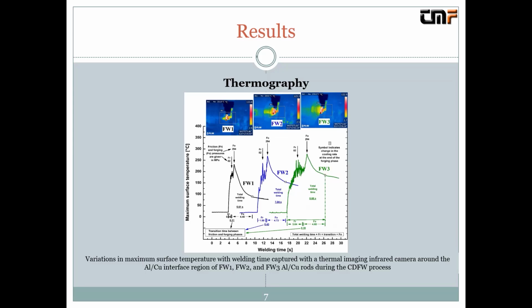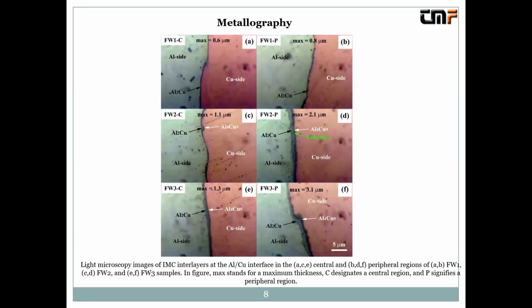And what's the importance of measuring those temperatures? It's to try to combine that information and to explain the kinetics of formation of intermetallic compounds. So in that manner, we have the higher temperatures for the third sample, and as you can see, all these changes which we followed were divided into two regions. First one was, let's say, the friction dominated region, and the second one is followed by forging. So at the beginning, there is friction which generates the important heat, and then when the samples were heated enough, the pressure begins to dominate and allows us to form